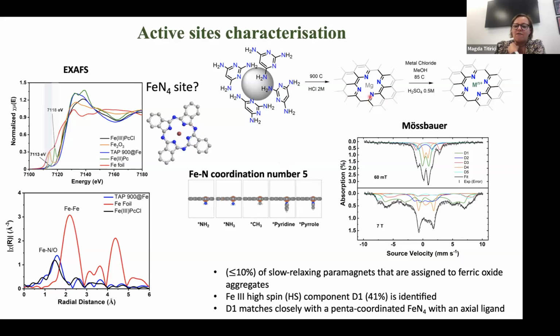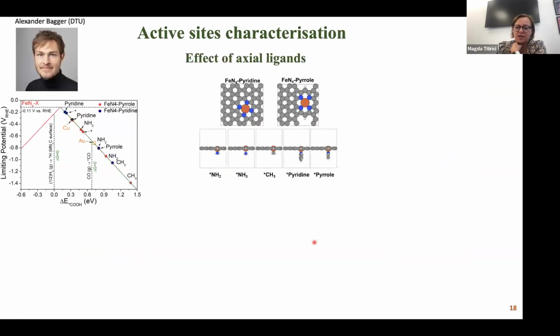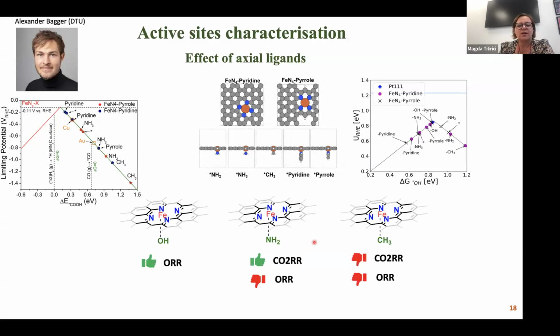So that means that we have 4 nitrogens coordinating with an iron, but the iron, or the metal, is in a 5 coordination state, which means that we can have another type of ligand coordinated to this. It's hard to know what that ligand is, so we went to our collaborator in Denmark, Alex Bagger, and he did some DFT calculation, and he figured out that in order to have a good ORR performance, to be on top of this volcano plot, potentially we probably have an OH axial ligand, which is coordinated with a pyrrolic type of nitrogen.